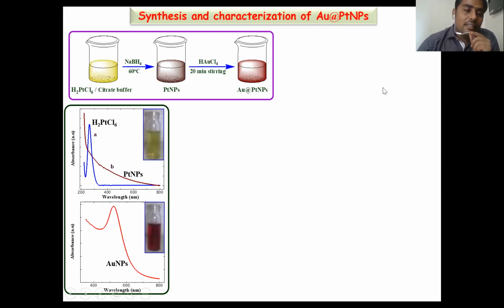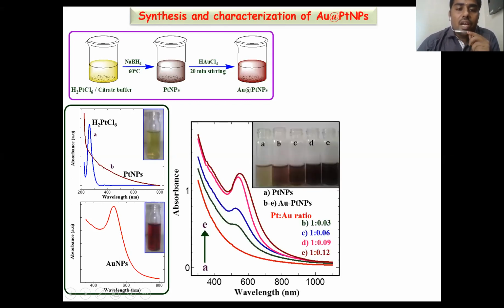As we discussed already, the platinum nanoparticles do not exhibit any SPR in the visible region. The platinum chloride exhibits metal to ligand charge transfer, and the platinum nanoparticles do not exhibit any SPR, whereas the gold nanoparticles exhibit the SPR band in the region of 520 nanometer. The color of the platinum nanoparticle solution is brownish yellow, and the gold nanoparticle solution is brown red, wine red color. So we monitored the formation of gold platinum bimetallic nanoparticles by the addition of auric acid to the platinum nanoparticles with the help of UV visible spectrum.